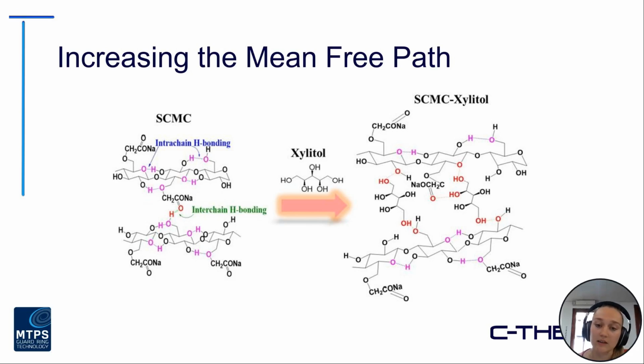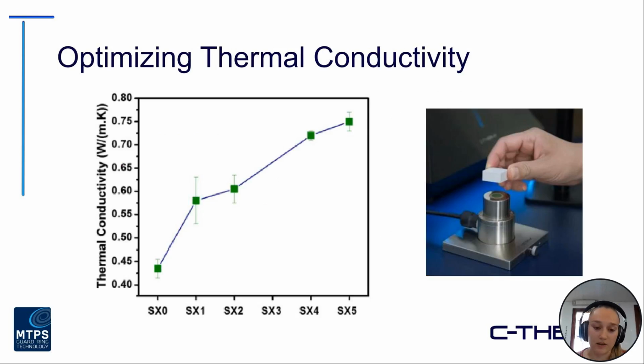So they took their SCMC sample. They actually added some xylitol into the sample to increase the mean free path. And by doing that, we see here on screen that they actually were able to optimize the thermal conductivity. What they did to test this sample was they used the modified transient plane source method, MTPS. This tests according to ASTM D7984. And you'll see that picture on the right of the screen there. That's the MTPS sensor, and that's a picture of a person placing the sample on top of the sensor.